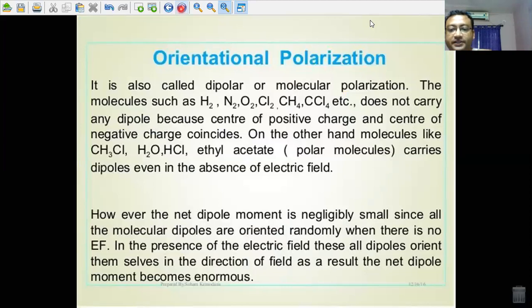So, this is the basic phenomenon of orientational polarizability. The net effect is that each polar molecule is a small charge dipole which aligns with the applied electric field and influences the total electric field both inside and outside the material. And the total polarization of a given material may arise from a combination of electronic, ionic, and orientational polarizability.